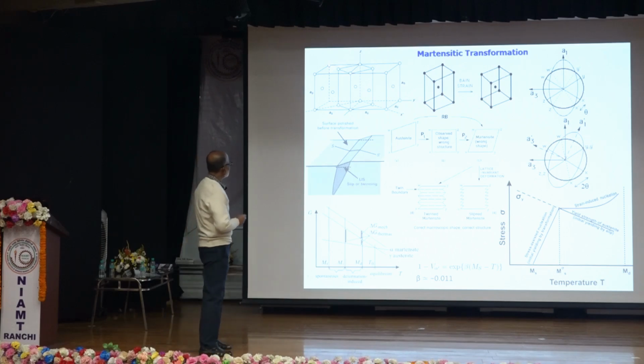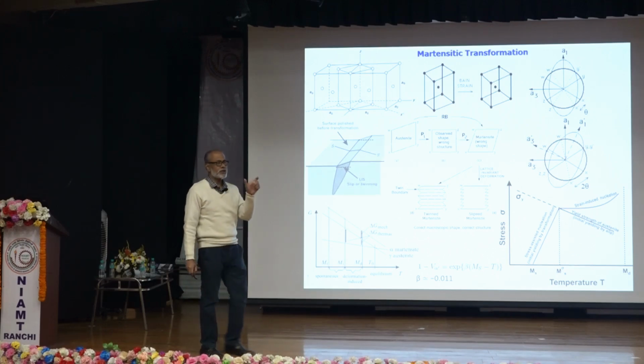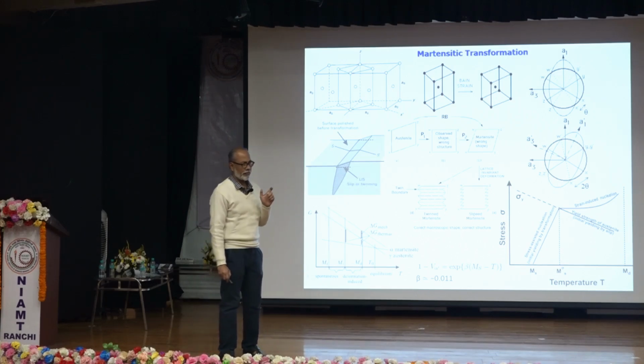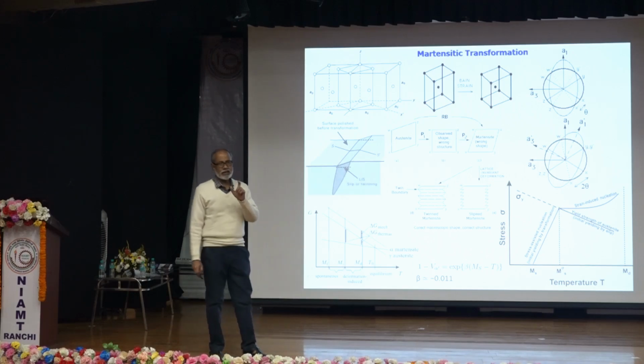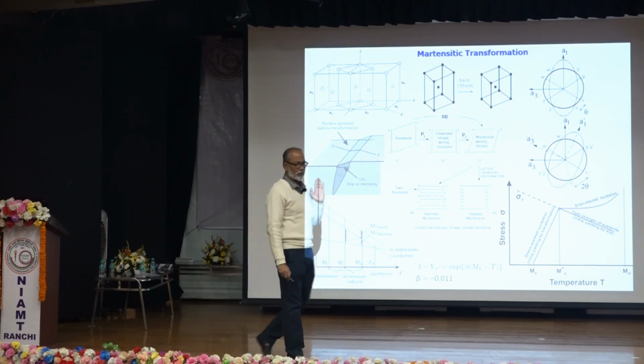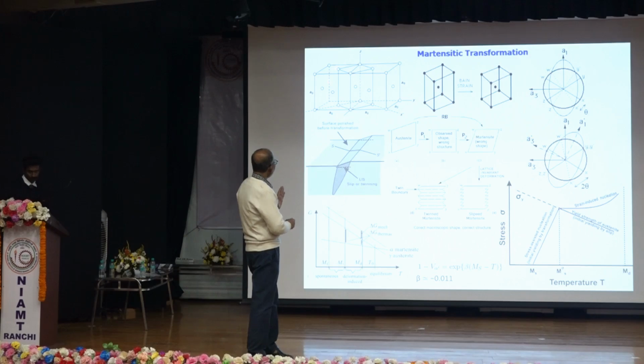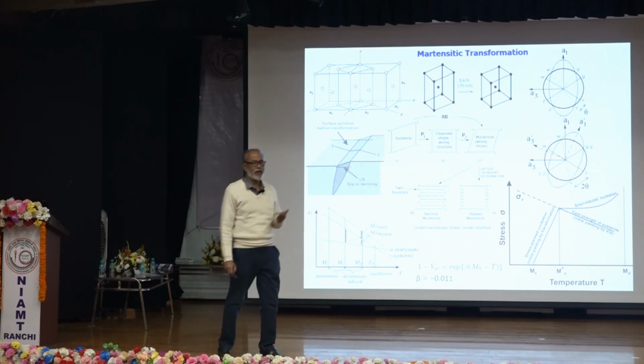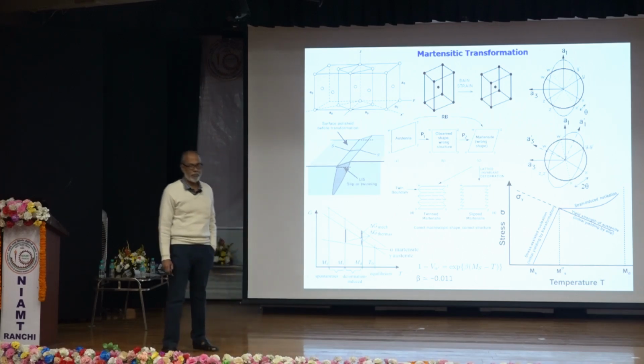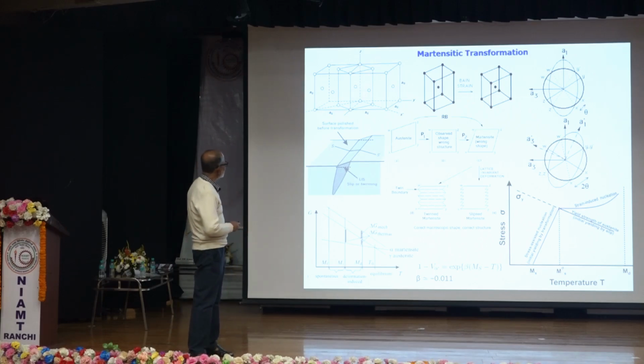Now, Bain had shown that it is possible to identify a body-centered cubic cell within the combination of these two face-centered cubic unit cells, right? So it is possible that the face-centered cubic structure may transform to body-centered cubic structure without any significant movement of atoms. It is well delineated within the FCC structure with the atomic locations which were there in FCC. But this can be necessary but not sufficient. For any transformation to take place, we need a surface. There has to be something which will create an interface between these two entities. This is ferrite and FCC austenite. So Bain proposed a model where he considered a homogeneous shear.